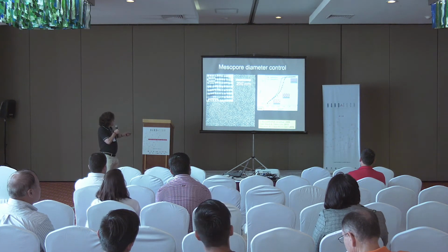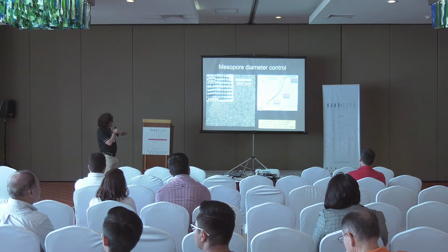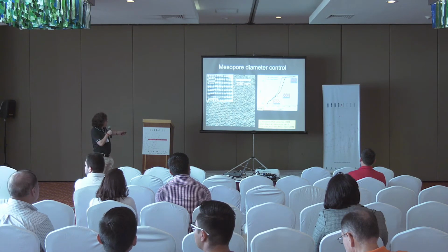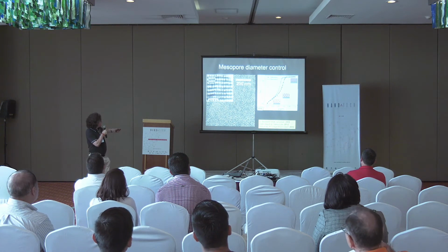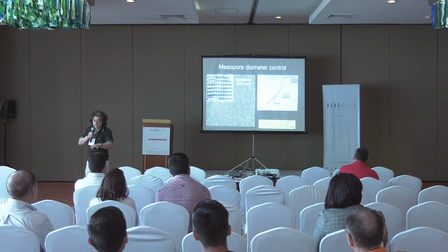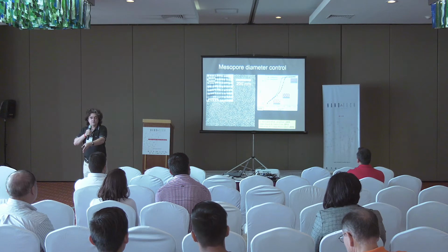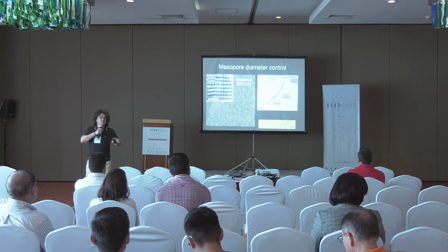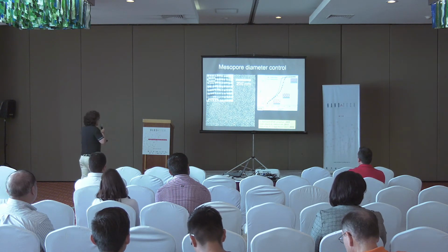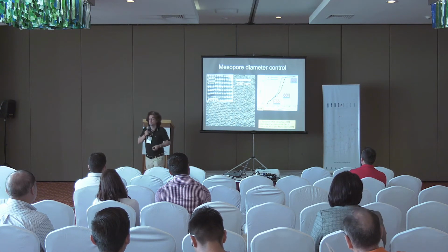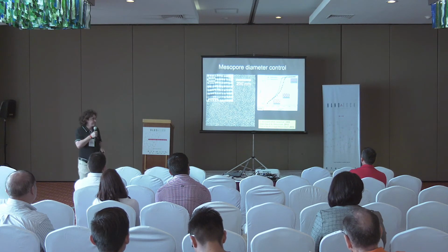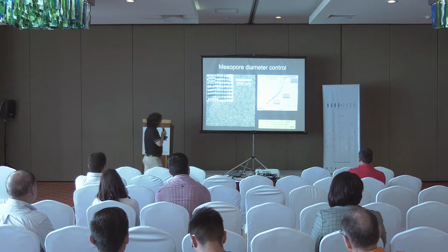This is scanning electron microscopy. You see here the surface of such a film. You see the pores, which are regularly oriented. You see maybe some domains. These pores are in this domain, these pores maybe in this domain. But globally, what a cell sees when it's landing there is, oh, there are craters at 4 nanometer distances, or 12 nanometers, or 9. We will have a different behavior because the proteins will have a different interaction with that surface. So we can determine very well the porosity here by using adsorption and desorption. But adsorption and desorption can be done optically using, for example, ellipsometry. So you can get very, very precise